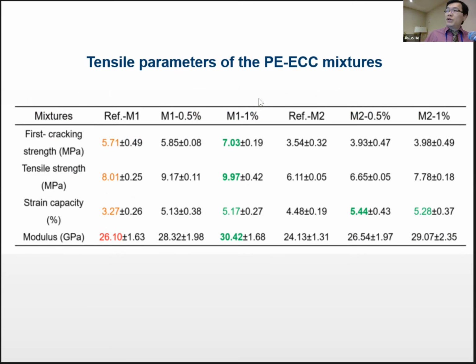So you can see that we derive the first cracking strength, which is very important. Usually you don't want the first crack to occur until it's totally necessary. And then you have the tensile strength, the strain capacity, and modulus. You want all these parameters to be high.